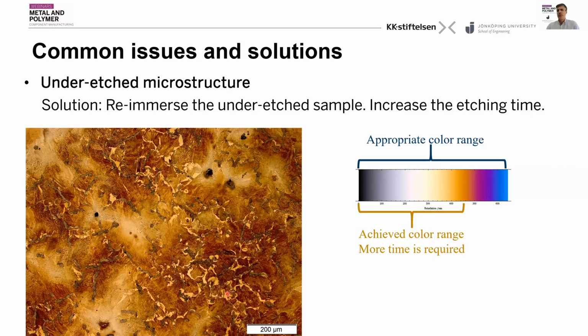There are a few problems that can occur when we are doing the color etching technique. The first is that after the etching, we get an under-etched microstructure. As we can see in this micrograph, the achieved color range is smaller than the targeted color range needed to reveal all the different microstructure features. A solution to this is to immerse the under-etched sample again and wait a little bit more, and also to increase the etching time for the next one.